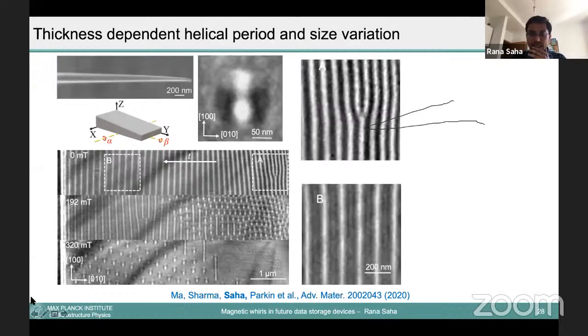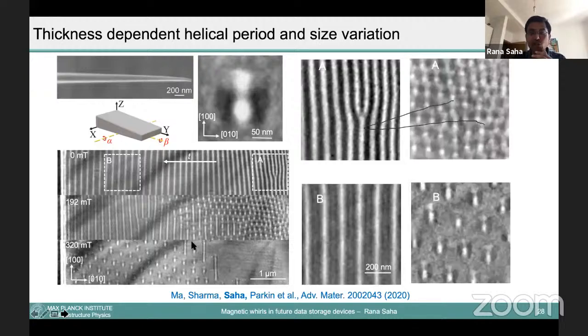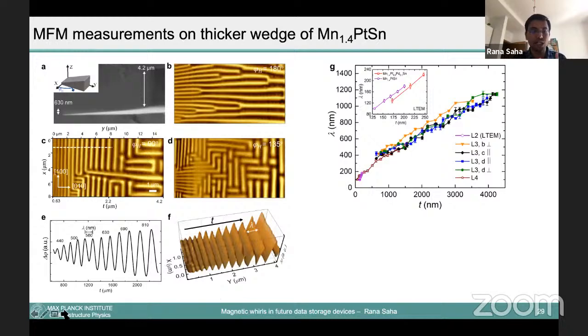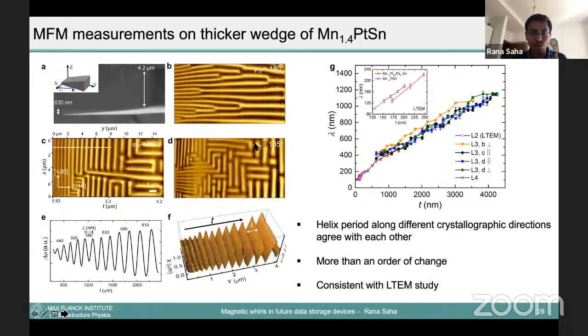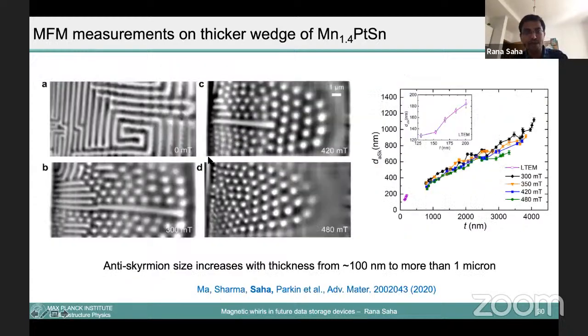So what we see here is that by tuning the thickness of the material, you can see the thinner part has a smaller size, and the thicker part has a larger antiskyrmion. In this way, you can tune. And also you can see the size of the skyrmion, from the left side to the right side, actually increases. So you can see this is the thickness.